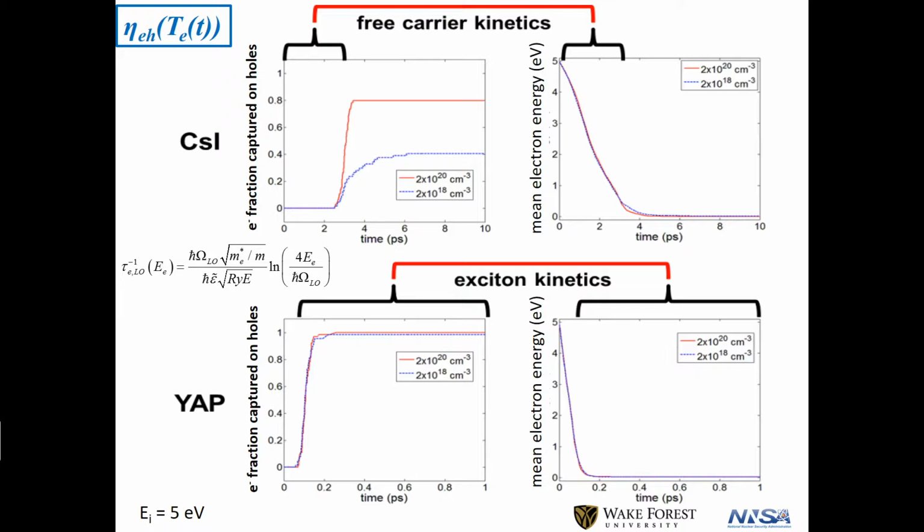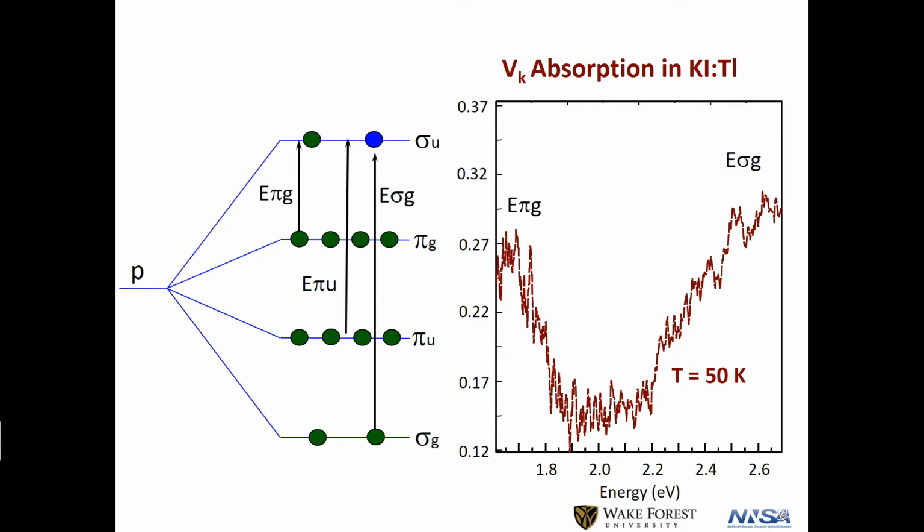I won't dwell on it, but we believe that's half, or maybe 60%, of the reason: in this material the carriers were remaining hot, and in oxides generally it's that light oxygen atom that pushes all the oxides down to the really fast cooling rate. So they cool, they do form excitons very quickly, and that's what we see interacting.